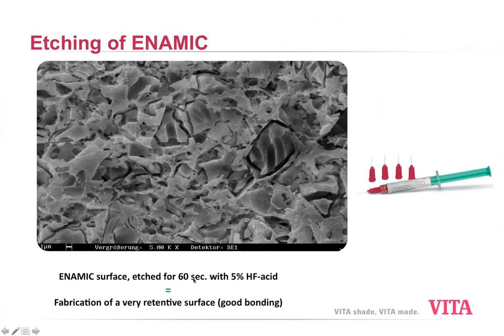VITA is recommending acid etching for 60 seconds with 5% hydrofluoric acid. If you have an 8% hydrofluoric acid, then you cut that down appropriately. Everybody has different acid strengths, so you have to look at the strength of the acid, just like you would if you're bonding in a porcelain crown or ceramic crown. Depending upon the acid concentration, you need to adjust the acid etching time.